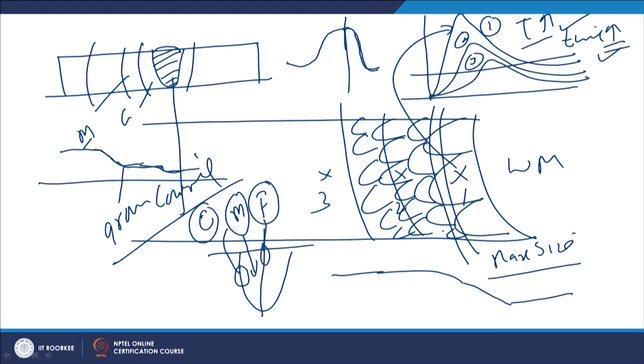So, when the metal is strengthened primarily by grain refinement, in case of fusion welding, the heat affected zone will be showing the reduction in hardness due to the grain coarsening, while the weld metal will be showing the variation in hardness as per the grain size. The grain size will be minimum at the center. So, hardness will also be maximum at the center, and then it will be reducing on either side as per the grain size of the metal.